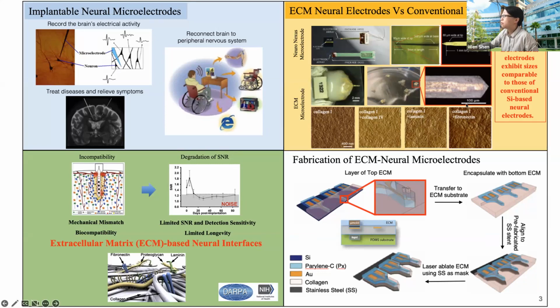silicon microelectrodes. However, the materials and the surface structures of these ECM microelectrodes are significantly different. You can see the long fibrous structures of collagen still remaining on these fabricated ECM materials. We believe these structures will support a more bio-friendly environment after implantation. Here is the fabrication process that we developed.